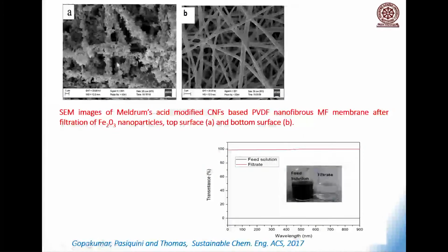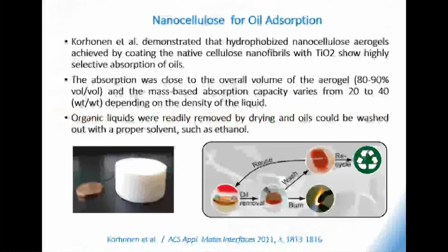You can see these are all iron oxide particles. We made a model system in my laboratory, water filled with iron oxide. The particle size was 50 to 100 nanometer. You can see all the suspended particles were stopped at the top surface of the filter. Simply by such a solution, the pore size was only something like 8 nanometer once you coat the surface of the filter. And you see the bottom part of the filter, this is PVDF. So using this filter, dear friends, we could filter out all the suspended particles in water.